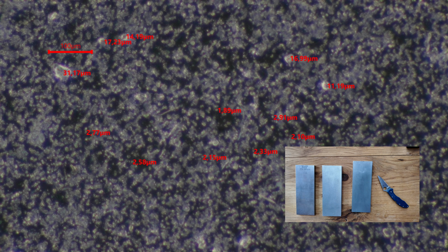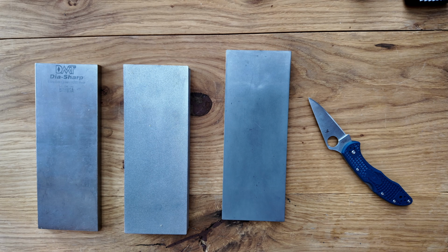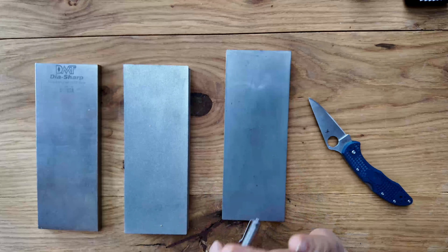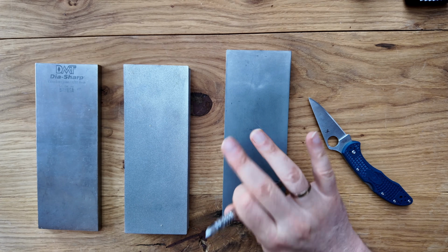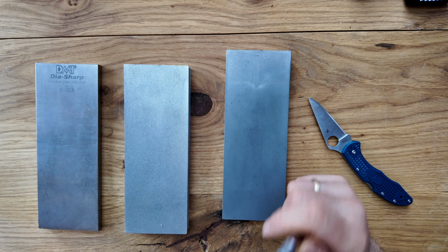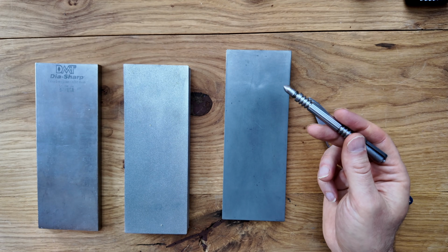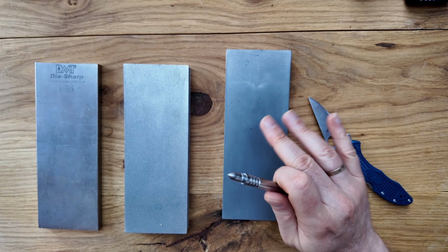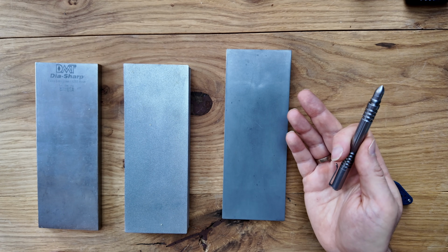So here I need to be clear about what I can and cannot determine from the image. The 31 micron feature has a different visual character. It looks smoother and brighter than the surrounding diamond field. That looks more like diamond tear out or an exposed nickel blob than an actual 31 micron diamond grain sitting at an 8000 surface. The 11 to 17 micron features, those are harder to call. If those are actual diamond grains, they are 1000 grit particles on an 8000 surface, which would be grit contamination either way. If they are tear out debris or nickel artifacts, they are just cosmetic imperfections.